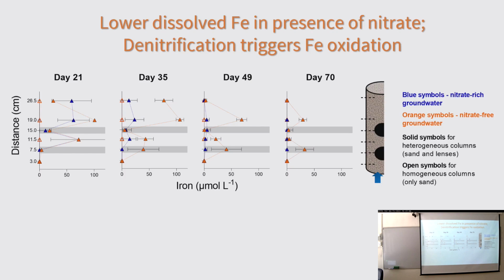That suggests that the process of denitrification that's taking place in the heterogeneous columns in the presence of nitrate, the denitrification is coupled to the oxidation of ferrous iron, which is taking out that iron 2 from the aqueous phase and moving it into the solid phase as iron 3. So after seeing these results, we were interested to look into the solid phase chemistry of iron to see what differences we could identify.